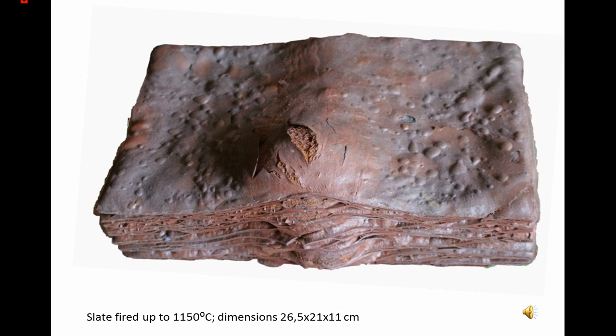These color changes indicate the ease or difficulty of access of oxygen during firing. The spongy interior also differs from the vitrified surface with regard to structural capacity, the surface being a lot tougher than the interior. The black slate did lose some weight, hardness, and mechanical resistance, becoming fragile and brittle, but acquires a very expressive telluric character, reflecting the intensity of the ceramic firing process.